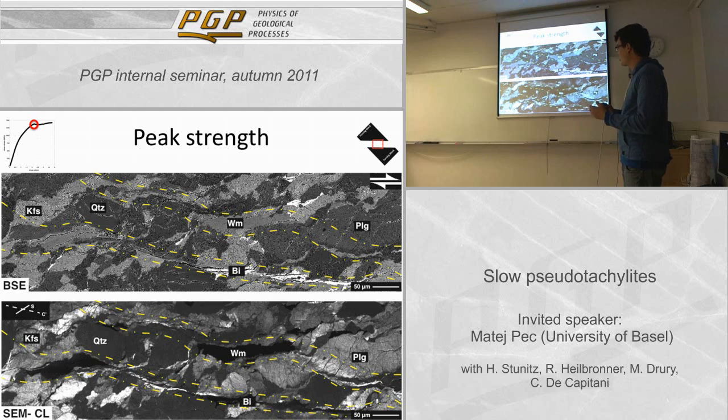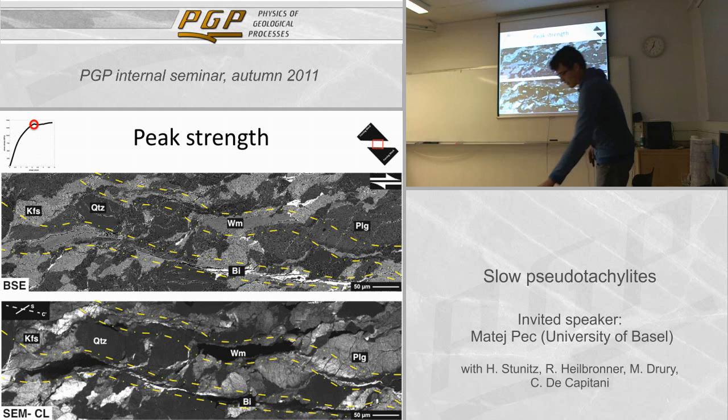And the material stores some elastic deformation and some permanent deformation. So if we have a material that is permanently deformed, it can't relax elastically as efficiently as a material that surrounds it and has a larger elastic component, which will tear this permanently deformed material apart.